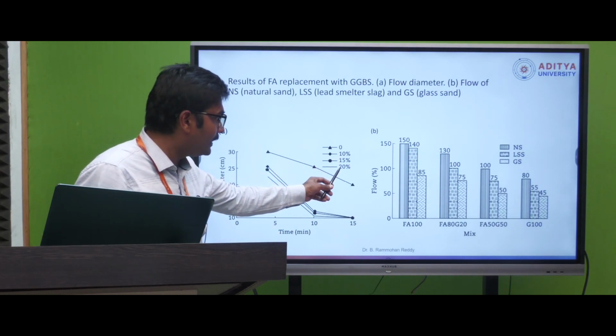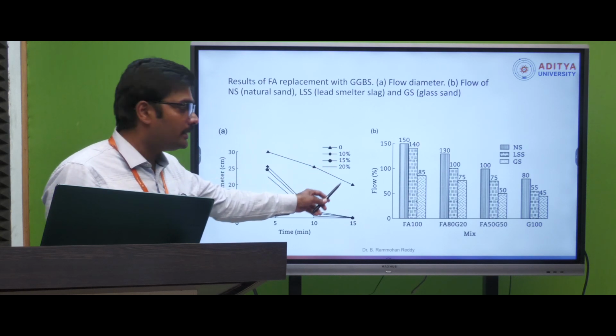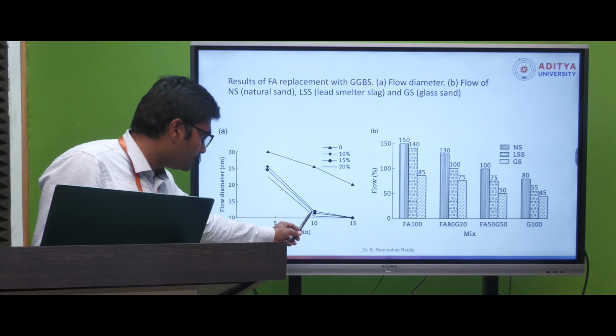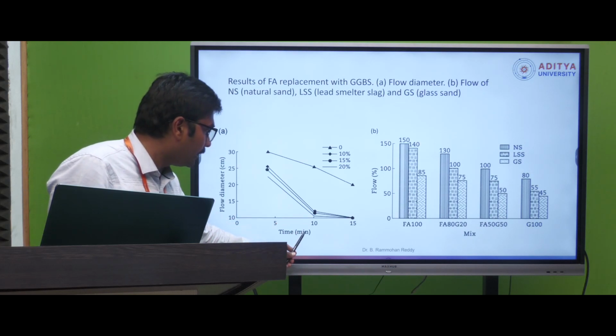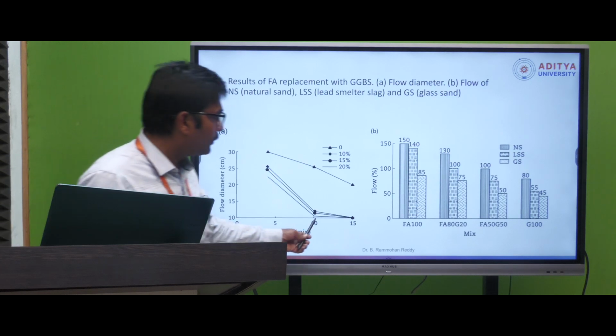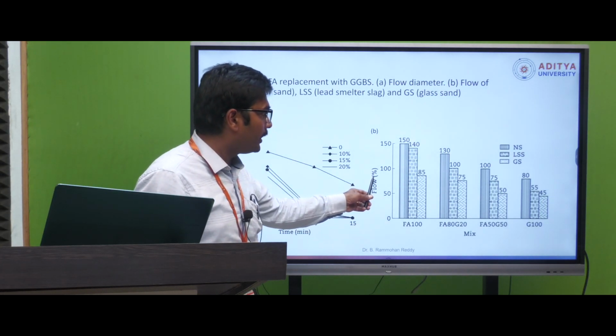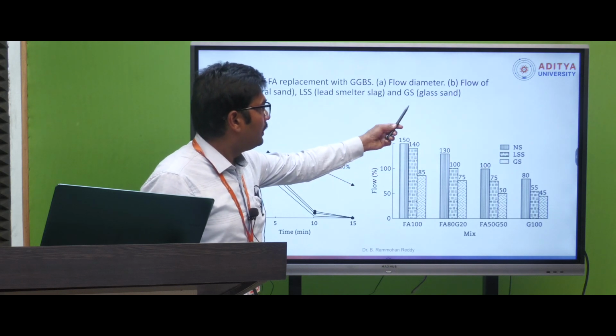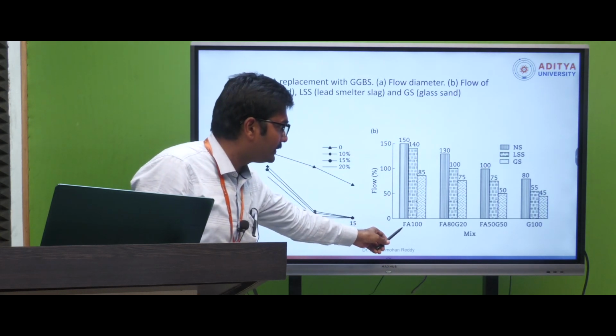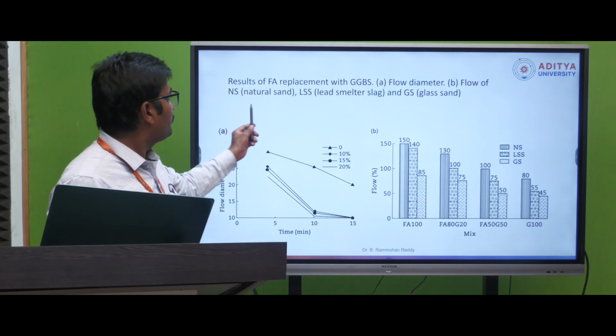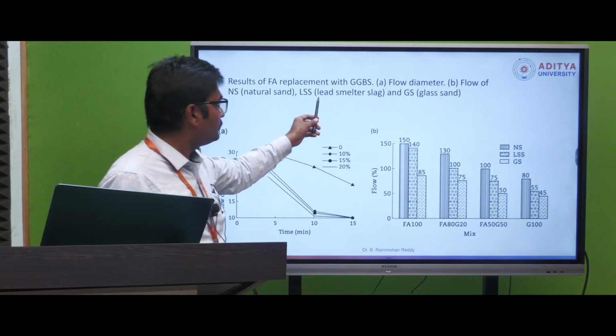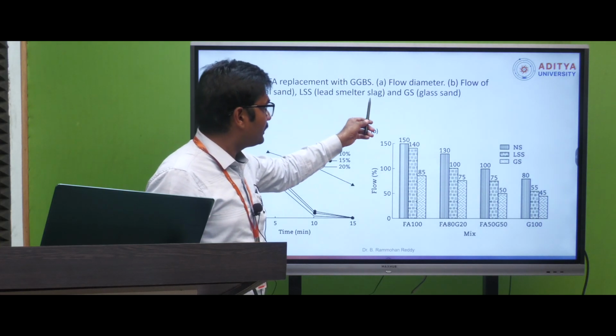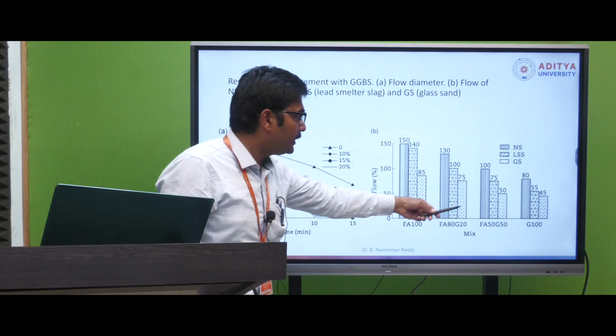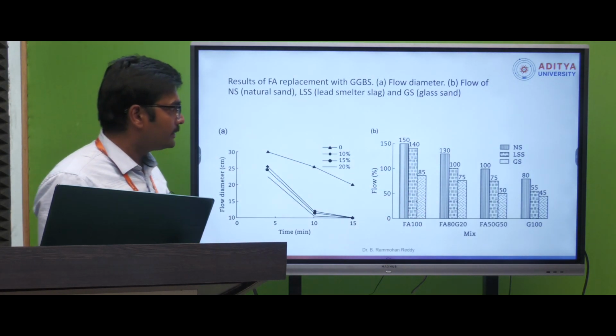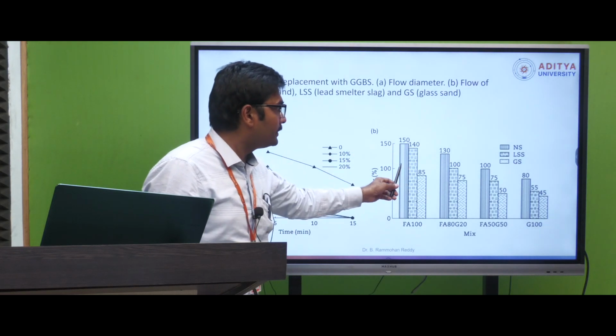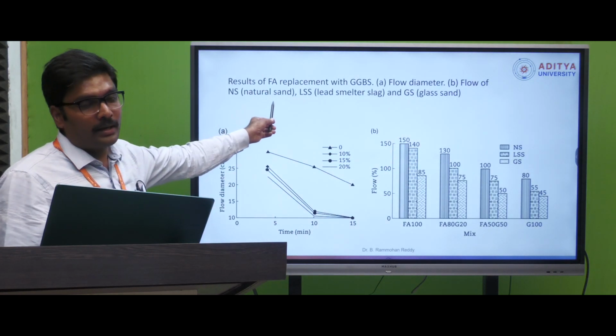And if the GGBS quantity is increased to 10%, 15% and 20%, the flow diameter is reduced, and it also takes less time for the flowability. And the flow percentage, if you can see, here for 100% fly ash based, flow by using natural sand, lead smelter slag and also glass sand. Compared to all of these, the flow percentage is less if you use glass sand, and the flow percentage is good if you are using natural sand for the geopolymer concrete.